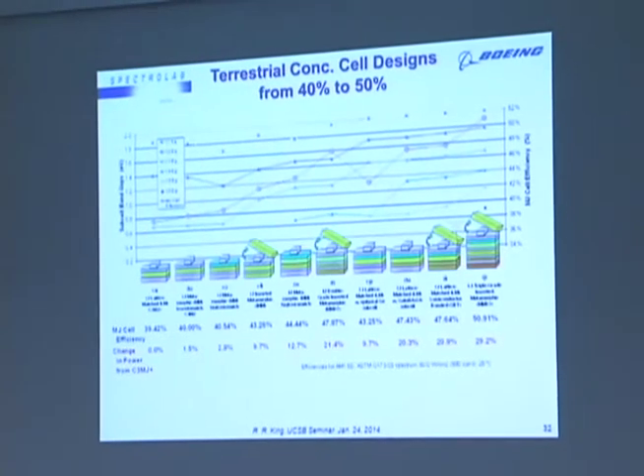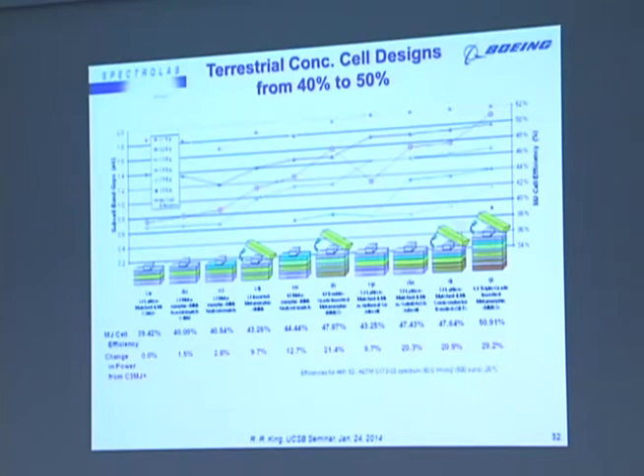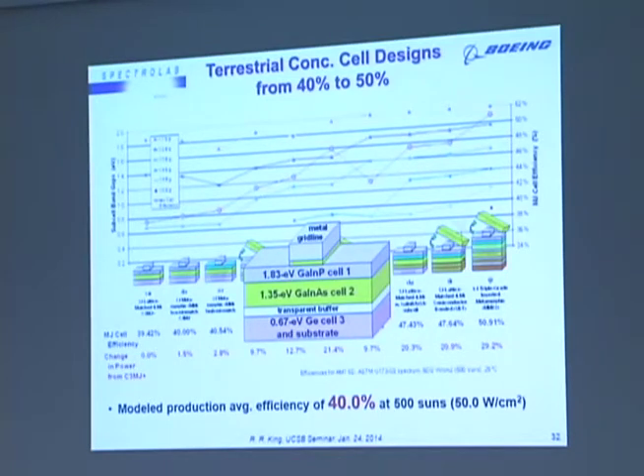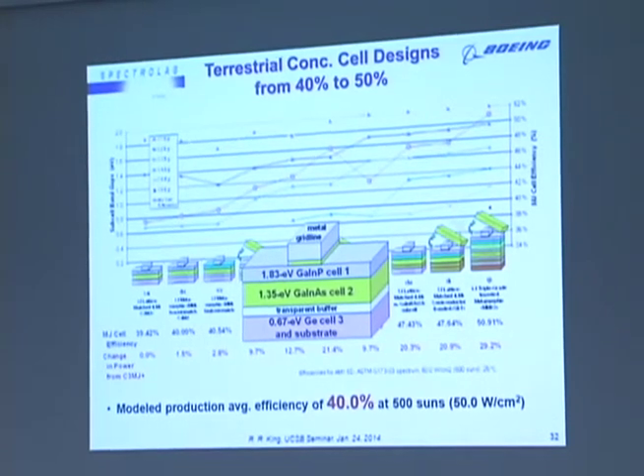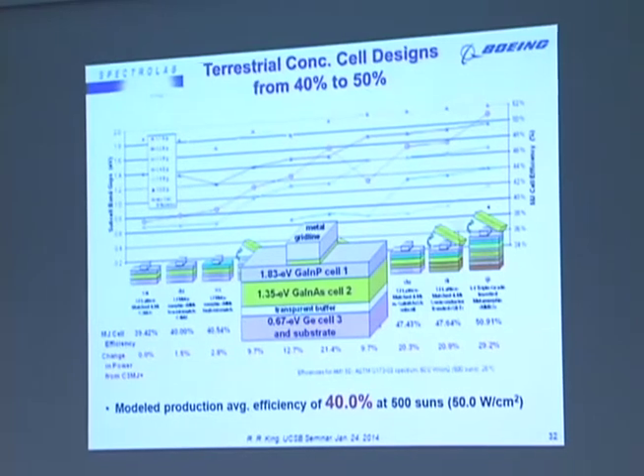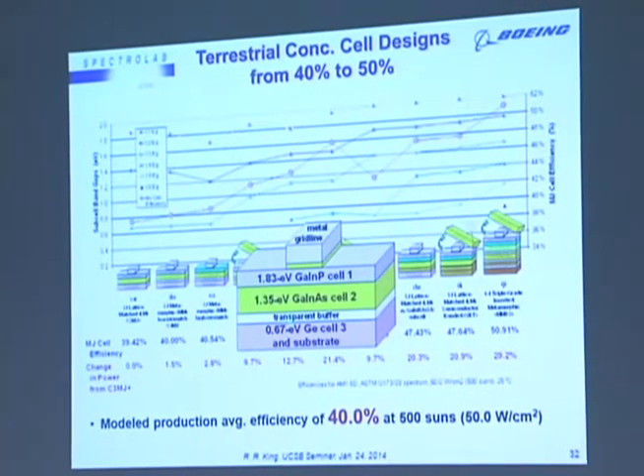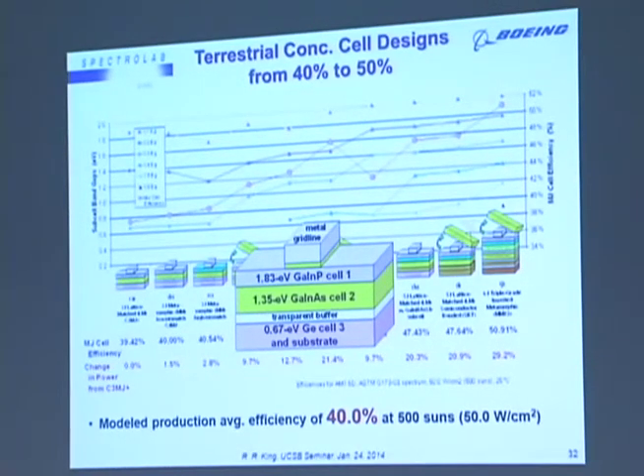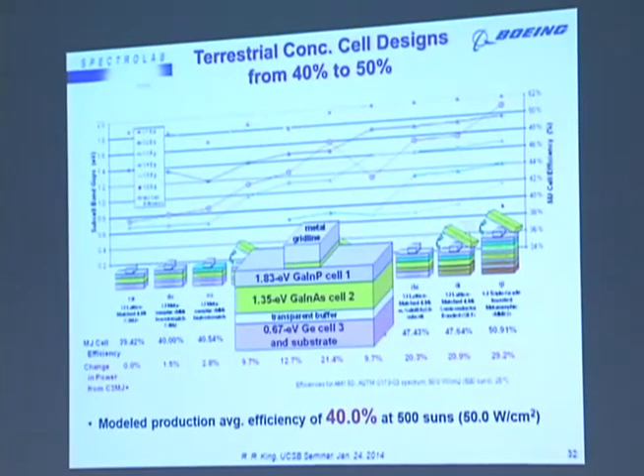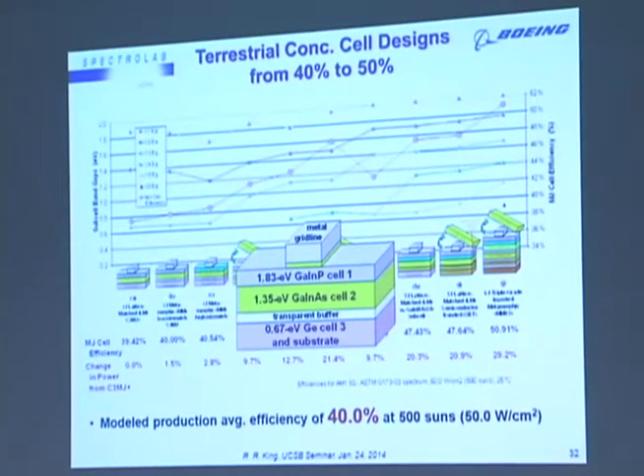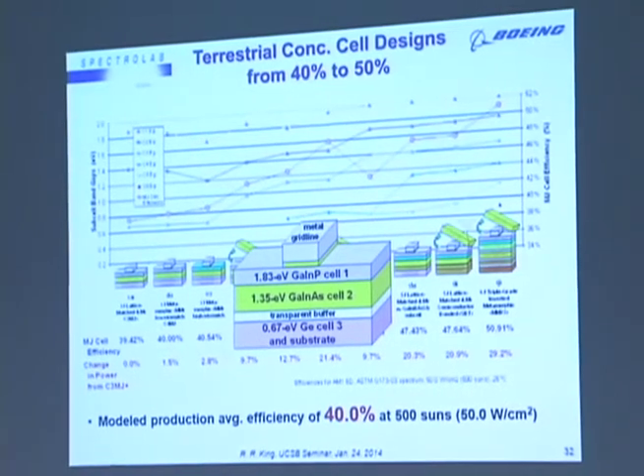So talking about metamorphic III-Vs, first of all, this is a plot of multijunction cell architectures going from about 40% efficiency up to 50% efficiency. And so first off, a fairly standard 3-junction solar cell, which is now a production terrestrial concentrator solar cell, is shown in schematic here. It has a transparent metamorphic buffer that transitions from the smaller lattice constant of the germanium substrate to the larger lattice constant of the upper cells. And in this way we can achieve a lower band gap in the upper cells, which is advantageous for this specific spectrum that we have coming from sunlight. Those types of cells have, in practice and in this model, a production average efficiency of about 40% these days.